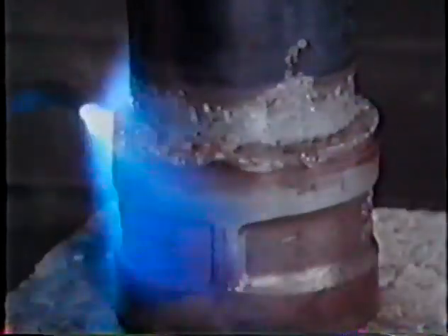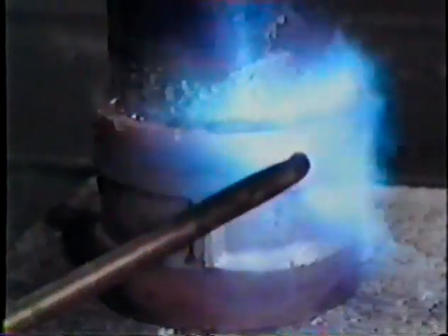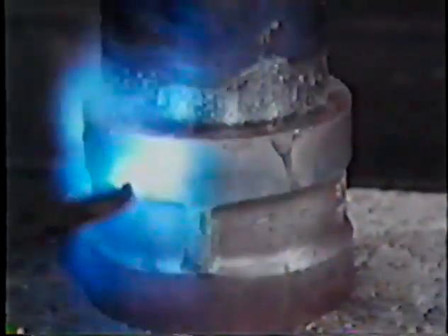The water in the flux boils at 212 degrees Fahrenheit. At 600 degrees Fahrenheit, the flux itself boils up and begins to melt. At 1,000 degrees, the flux is melted and has a transparent look. As the temperature hits 1,100 degrees, the flux turns to a clear liquid. Above this temperature, the alloy, not the flux, is your thermometer.